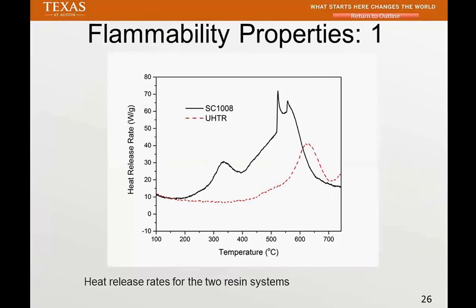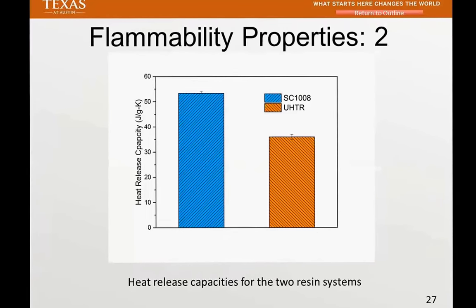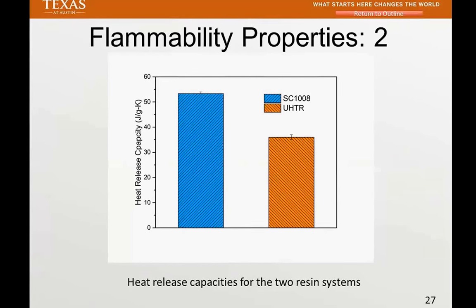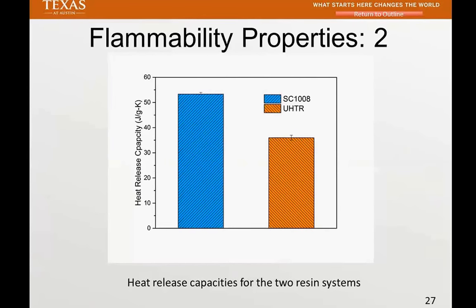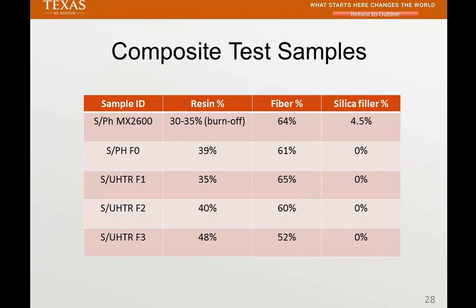So that's another good thing. Okay. Now we plot that. Basically one is lower than the other. You're comparing it to control. Then we start actually varying the resin, the fiber, and the filler for this particular free system that we made. There's no filler. This F0 is similar to what you actually compare with the Cytec material, except that you don't have a silica filler. So these are the ones that we are doing in the lab.